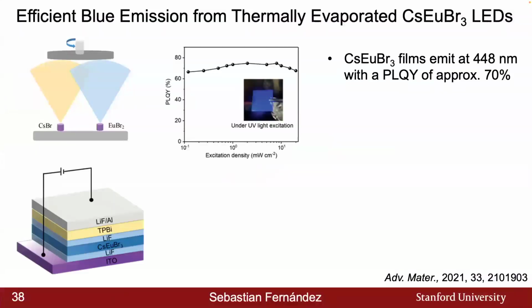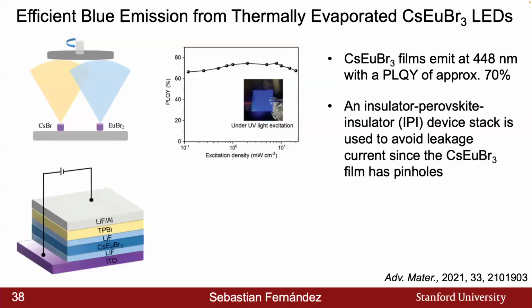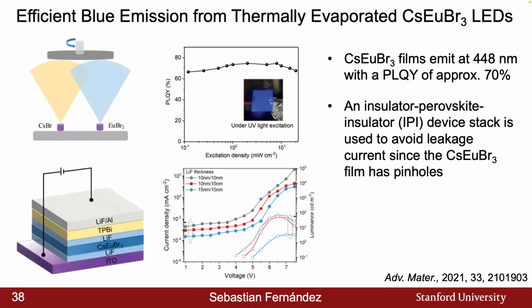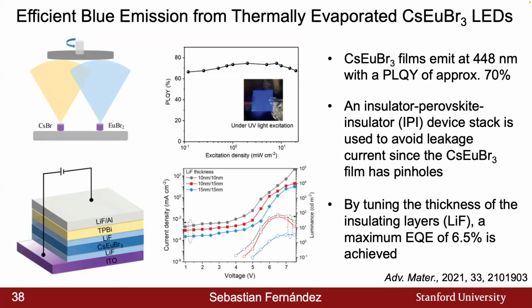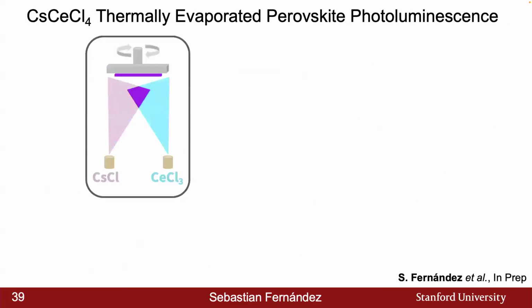Nice, okay. And so, yeah, by sandwiching the perovskite layer with these lithium fluoride underlayers as well, it's in order to avoid the amount of leakage current that might occur from the cesium europium bromide thin film. And then the authors showed that by simply tuning the thickness of these lithium fluoride layers, they were able to tune the device performance and eventually lead to a maximum external quantum efficiency of around 6.5% for this pure lead-free platform.